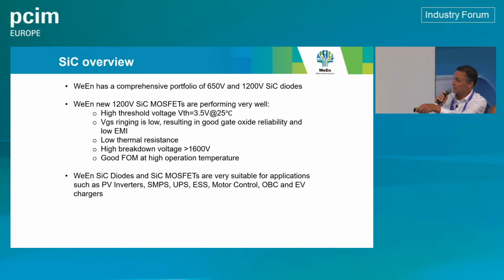The VGS ringing is very limited. This is good for gate oxide reliability and EMI. Low thermal resistance. Blocking voltage is very high, so for nominal 1200 volt parts we see blocking of around 1600 volt in real. And we have a very good figure of merit. Figure of merit is the multiplication of gate charge and RDS on.